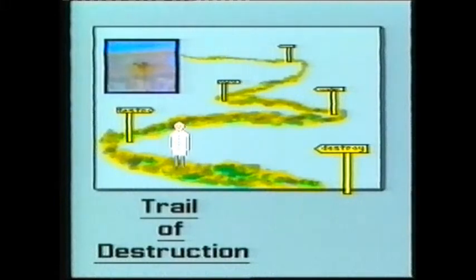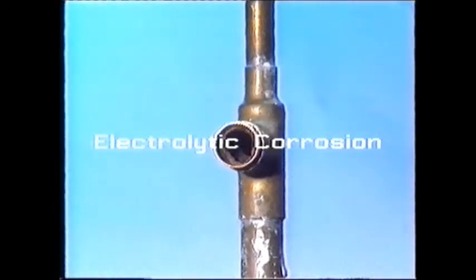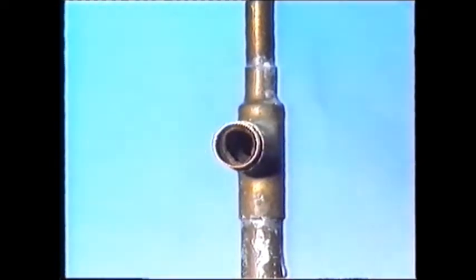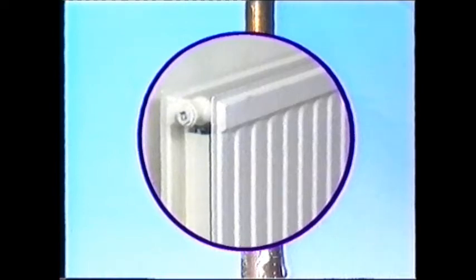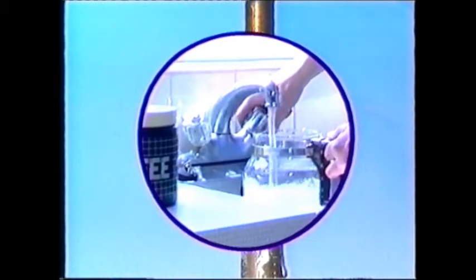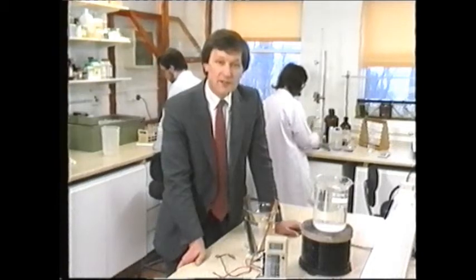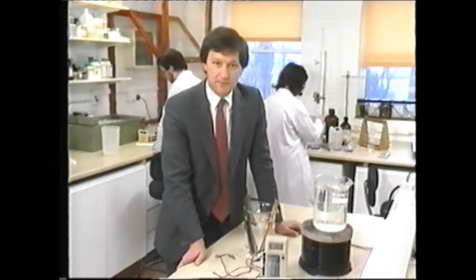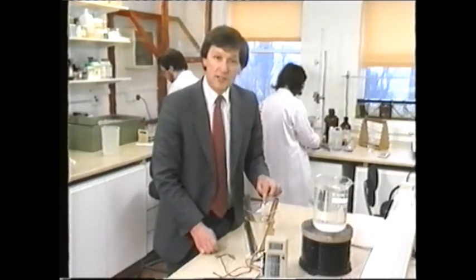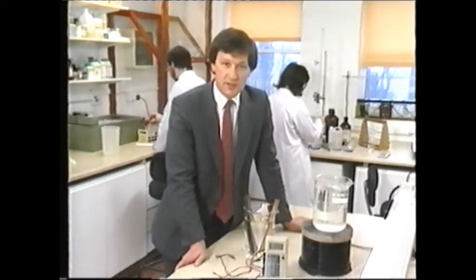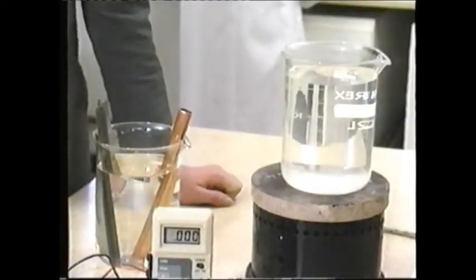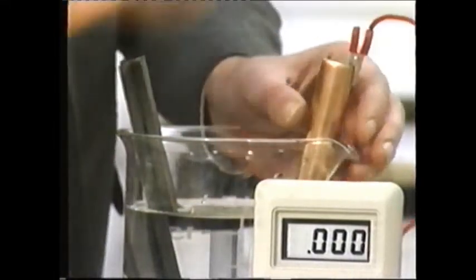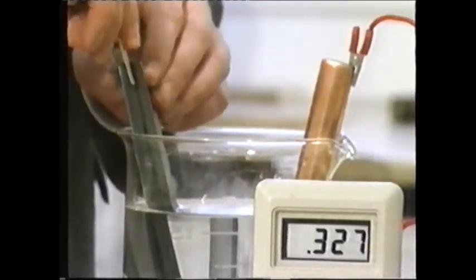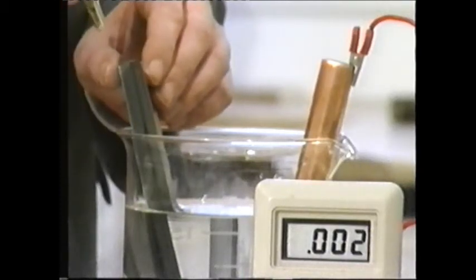But even in the virtual absence of oxygen, corrosion can still occur in the form of electrolytic corrosion. This is promoted by the presence of mixed metals, such as steel and copper, plus water acting as an electrolyte. The very elements that are basic to modern central heating systems. The mixed metals, connected by the water, cause a current to flow. This results in the least noble of the two metals, in this case steel, corroding. By connecting an ammeter to a piece of copper tubing and some steel from a radiator, the current can actually be read.